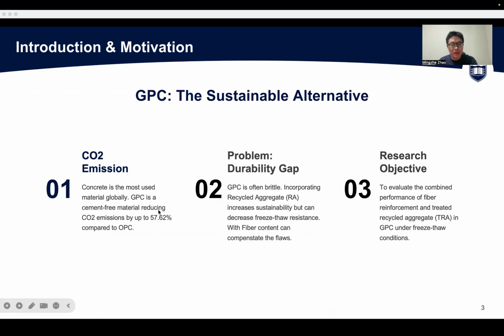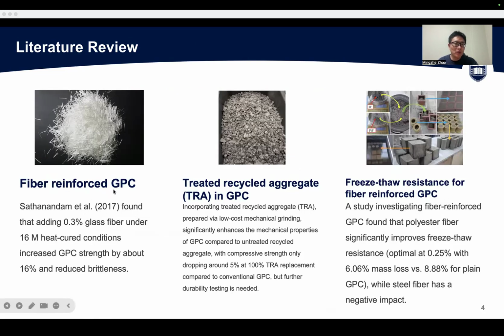So GPC is a sustainable alternative for concrete, because concrete is the most used material globally. But GPC is a cement-free material, reducing CO2 emissions by up to 57.62% compared to OPC. However, GPC also has some problems. It's often brittle, and incorporating recycled aggregate increases sustainability but can reduce freeze and thaw resistance. Fiber content can compensate for these flaws. So my research focused on the combined performance of fiber reinforcement and treated recycled aggregate in GPC under freeze and thaw conditions. Let's come to the literature review part.